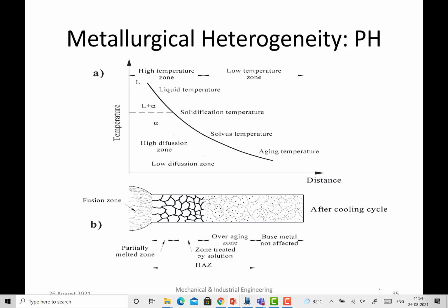Now if you see here, the base metal which is strengthened by the precipitation hardening is full of fine precipitates, you can say, and these fine precipitates are contributing towards the desired strength of the metal. So your hardness is really quite good in this zone. As you move towards the joint interface, you are noticing there is a rise in temperature as you approach. This is typical of the weld thermal cycle. As you approach towards the joint interface or weld nugget area, your temperature rise will be there. Increasing temperature will be causing the dissolution or overaging of these precipitates.